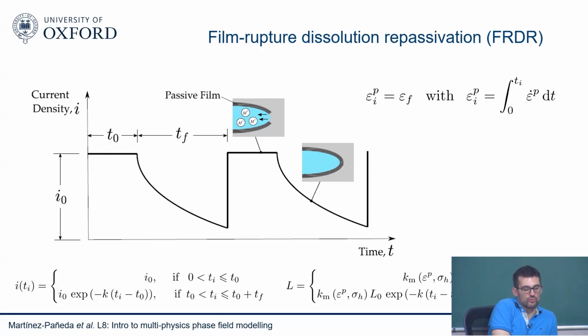But it's very difficult to resolve this film rupture process and repassivation from first principles, because this film is at an atomic scale, so it's a bit complicated. I'm hoping that working with atomistic people we can get in that direction, but it's a complicated topic. Again, this is a very small film, and you never know. It's difficult to describe from first principles. This is the point. So some degree of fitting in this case, I'm afraid, is needed.